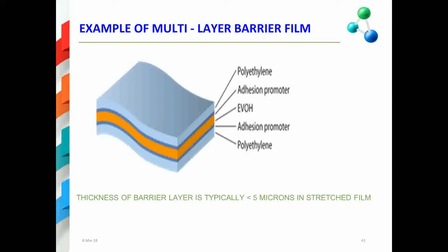Here is an example — a picture of a typical five-layer film that can provide barrier features to a product. The inner EVOH layer provides oxygen barrier in this film structure, along with serving other functions such as sealing features and perhaps printability. The PE layers can and do provide moisture barrier features to the film. There are also tie layers or adhesion promoters that need to be included in this film structure.